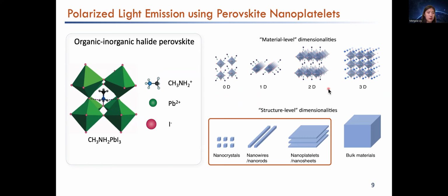They're both very important, and the material we are going to talk about today that is used as the light emitter is organic inorganic halide perovskite. This is a type of material that has a cubic or near cubic structure, where an organic molecule sits in the A site with lead halide octahedra sitting at the four corners. This material has been used heavily for photovoltaics in recent days. And one significant property of this material is its flexibility and tunability in structure. By using different organic molecules, the structures can be completely changed from 0 dimensions to 3 dimensions. The 3 dimensional form is called bulk material, and they can also be structured into nanoplatelets, nanowires, and nanocrystals.